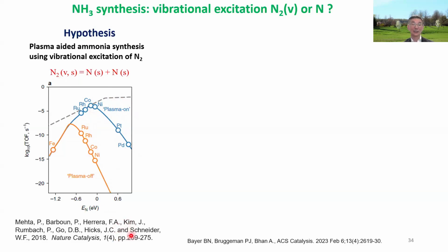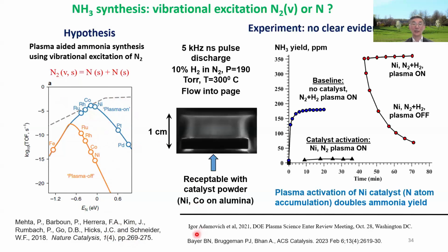Since then, a lot of people have tried to find how they can increase ammonia synthesis by orders of magnitude. My collaborator Igor Adamovich and my colleague Brandon all did a lot of this ammonia synthesis. What they found is that with plasma catalysis, with plasma, they can only increase the ammonia yield by a factor of 2 with vibrational excitation, no more. So what is the reason? What is the missing mechanism? Today there's no clear answer why not.